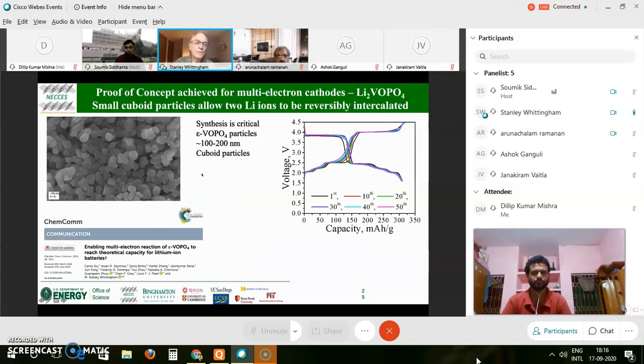And what we form are these nice cuboids, about 100 nanometer in size, all uniform. And using these materials, we then get this electrochemical behavior. You can see vanadium 5 to vanadium 4 at just under 4 volts, then vanadium 4 to vanadium 3 at between about 2.25 volts to just under 2 volts. And you'll see these bumps here. This is lithium ordering in the structure.